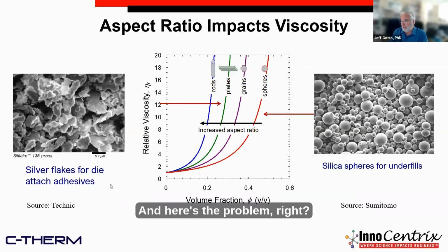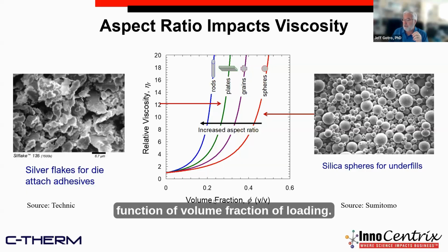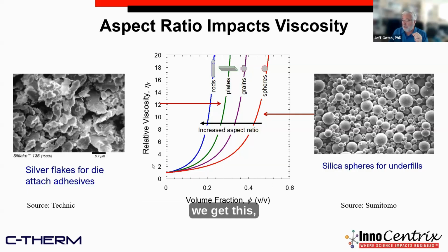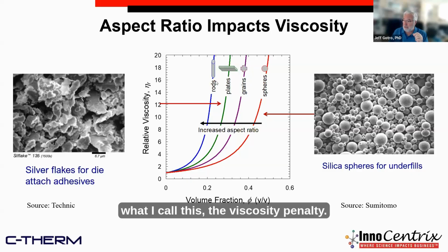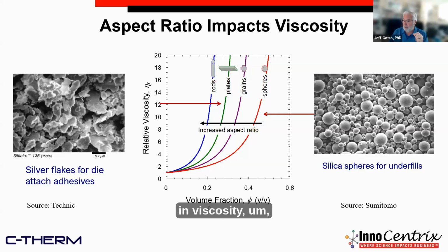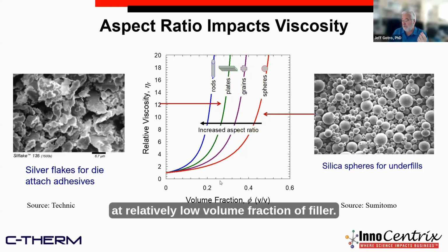And here's the problem, right? And you go, oh man, that boron nitride looks great. But boron nitride is platy, and silver flakes are platy. And what we have here is normalized viscosity as a function of volume fraction of loading. So as we increase the loading, we get what I call the viscosity penalty. So if you see here plates, which would be boron nitride and silver flakes, you get this very huge increase in viscosity at relatively low volume fraction of filler.